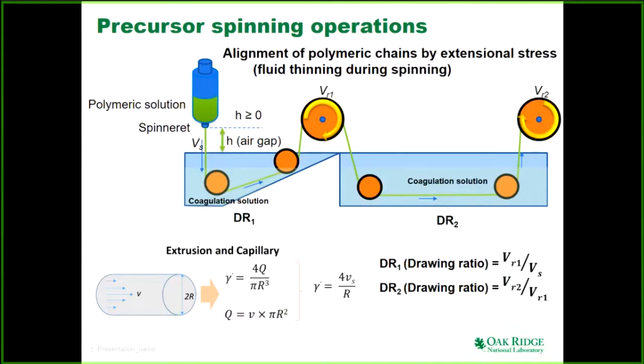Okay. So you have that syringe through which the jet, the green colored jet with velocity Vs, is coming into the coagulation bath. And then the polymer is in a solution, that is a polymeric solution we are talking about. It comes into the coagulation bath, and during coagulation, it precipitates. Now, whenever it precipitates, we want to pull it along the fiber movement direction. We cannot pull it too much because the fiber is weak at that stage.